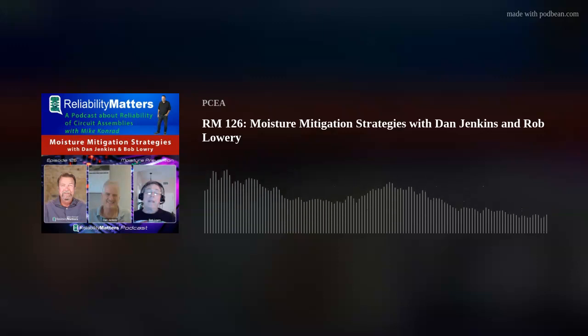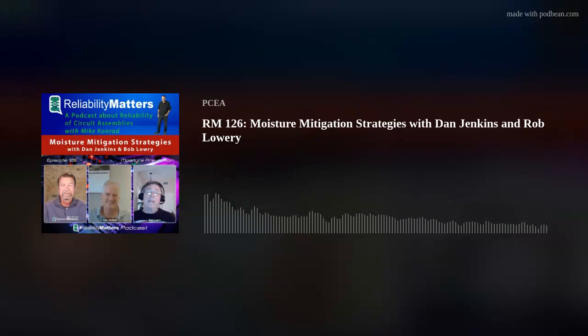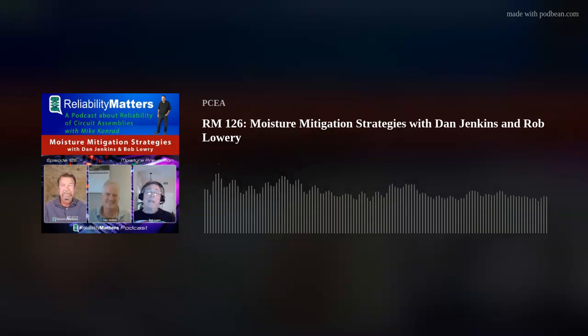IPC recently changed the J-standard 001H, section eight of that standard, to call for a new method of determining cleanliness called an objective evidence standard. There's not one magic number that applies to an industry as there used to be. Now you take a test coupon similar to your assembly in terms of soldering materials, reflow profile, and component types, and you reflow it, then subject it to a 168-hour surface insulation resistance test under heat and humidity. If the board is very clean, that heat and humidity is not going to result in an ECM — electrochemical migration — event. If the board has residue on it, it has a greater chance of failing one times ten to the eighth ohms within that time period under that stress condition.